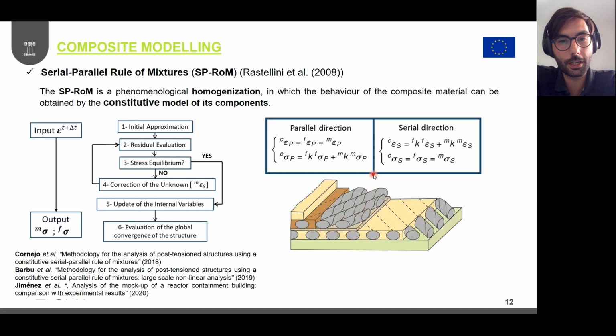What does it mean? Well, in the direction of the fibers, we want to fulfill a parallel behavior, which means that strains are the same. But in the other directions, orthogonal to the fiber directions, we want to model a serial behavior in which the stresses are the same. And in order to solve this, we cannot do it explicitly, so we do it in an implicit way via a Newton-Raphson update of all the variables until we converge. And this works pretty well, and we have applied this to many, many different composite materials. For example, reinforced or pre-stressed concrete in nuclear plants, and also glass fiber reinforced polymer, etc.